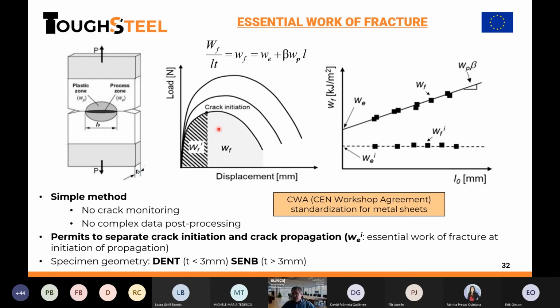So if we plot the energy divided by the area for different specimens having different ligament length, and we get a linear trend, the interception of this linear trend with the y-axis gives us the fracture toughness. Of course, if we don't have a linear relation, we have to think about what happens here, because this model will not work. But if we follow this, then this is it.